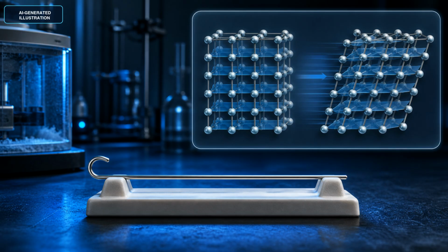The high-temperature phase is called austenite. In a nitinol actuator, that is the parent arrangement whose geometry was shape-set while the alloy was hot. Cool the wire through its martensitic transformation, and the atoms shift cooperatively into a lower symmetry arrangement called martensite. This is a diffusionless change. Neighboring planes move together rather than atoms wandering long distances and changing the alloy's composition.